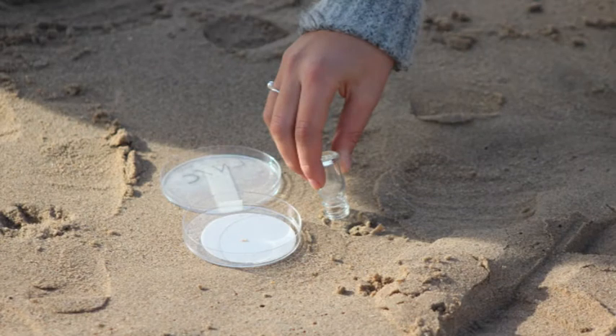We sample very small amounts using a glass tube that is essentially a core. We stick that into the sediment at the high water mark. We then close or seal these vials with a metal cap, so there's no plastic contamination. Take it back to the lab, then use a high density saline extraction procedure that floats the particles to the surface. We can then remove these, filter the water, and then observe or analyze the filters for plastic particles.